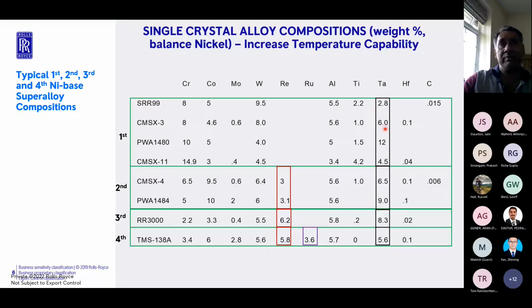The main reason being tantalum is a solid solution strengthener. So it basically makes the alloy, the gamma phase or the matrix phase of these alloys, quite strong. So the main difference between earlier alloys or polycrystalline alloys and the first generation single crystal alloys is the addition of tantalum as a solid solution strengthener or as a refractory metal.